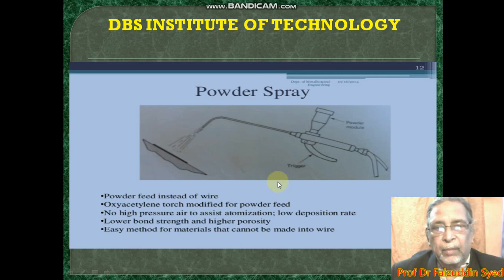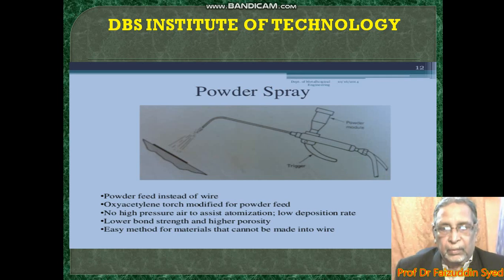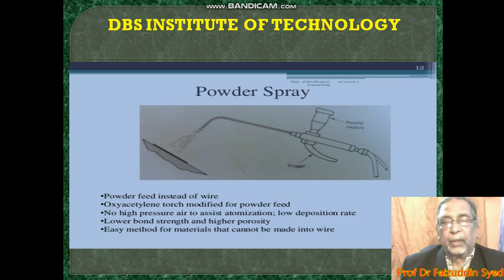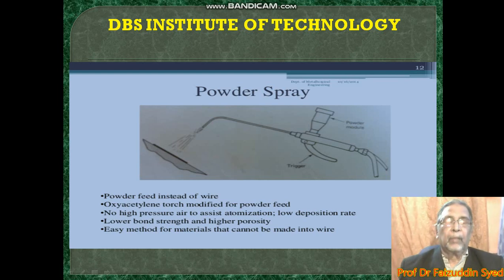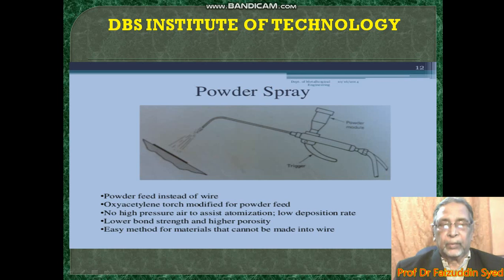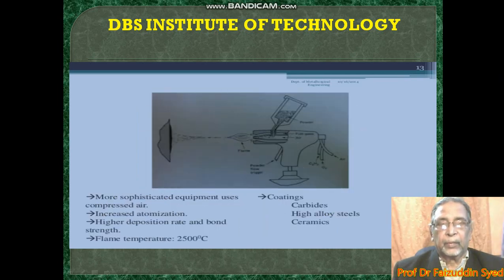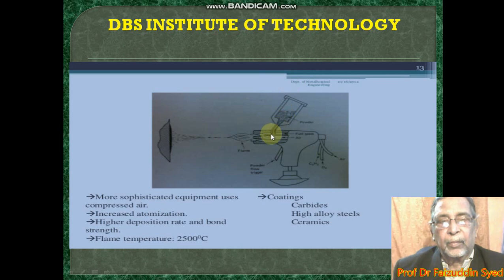No high pressure air to assist atomization. You are not using any high pressure for the purpose of atomization. Low deposition rate, lower bond strength and higher porosity can be obtained here. It's a very easy method for materials that cannot be made into wire. This is a metal spray gun where we are using the powder here, not the wire. You can see the metal spray gun here. Above it there is a hopper for pouring the powder.